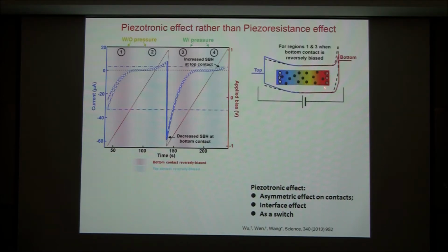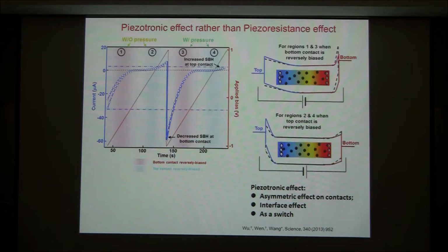It's because of the asymmetric distribution of charge at the two ends here. This is non-symmetric. Which way the current flows depends on the local polar charge sign here, which dictates the transport across this interface. And in such a case, you can manipulate the transport. If you say this is forward bias, this is reverse bias, you change the barrier height differently, changing the characteristic of the current.